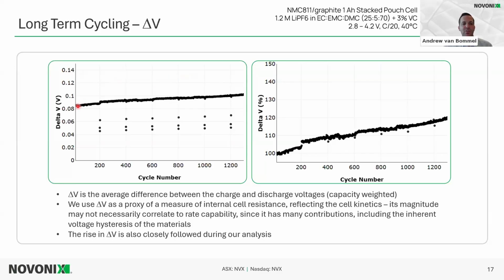What this is giving is a proxy measure of internal cell resistance, or it reflects the cell kinetics. So if we compare one cell to another, we have to use caution when looking at the magnitude of the delta V, because some of that delta V could be from the inherent hysteresis of the materials. So if we're looking at a cathode material like a lithium-rich oxide, or those LMR materials, as some call them, we know that has a lot of voltage hysteresis, so it's expected that that delta V will be higher. That's not necessarily correlating to any change in the rate capability. So it's important to also look at the normalized delta V. In this way, we can see any delta V growth, and we follow this closely during cycling.